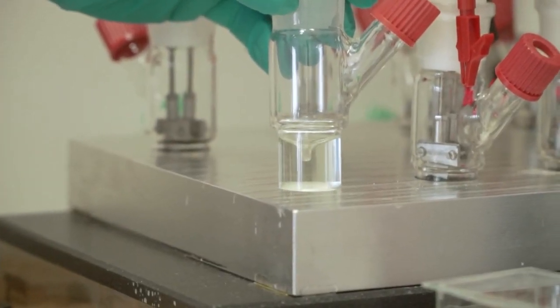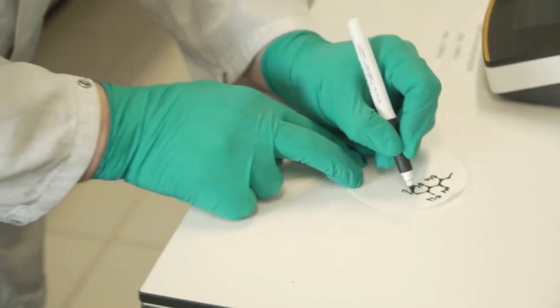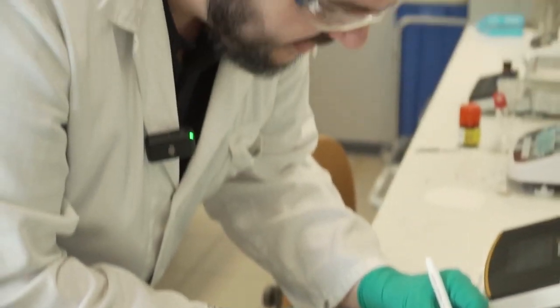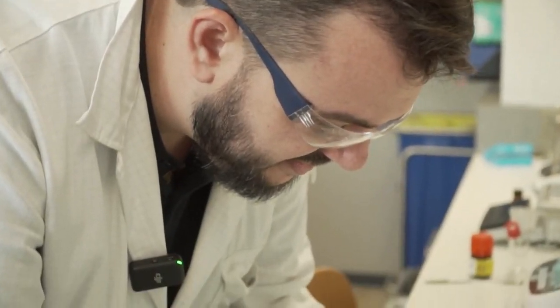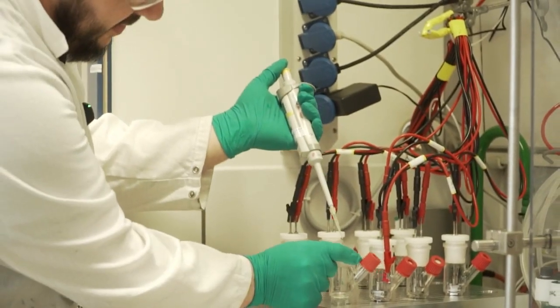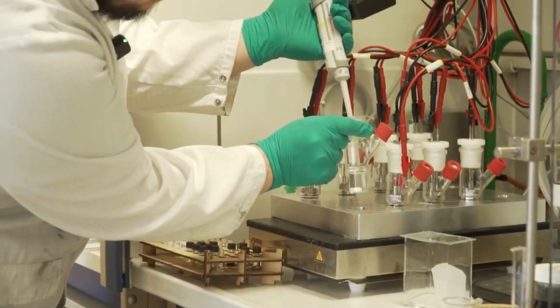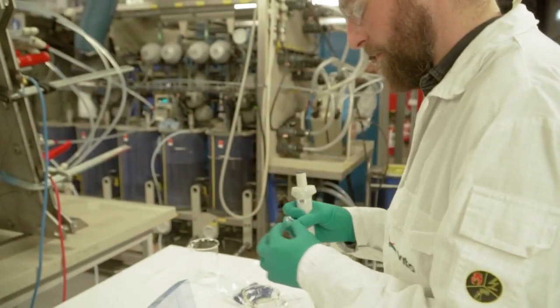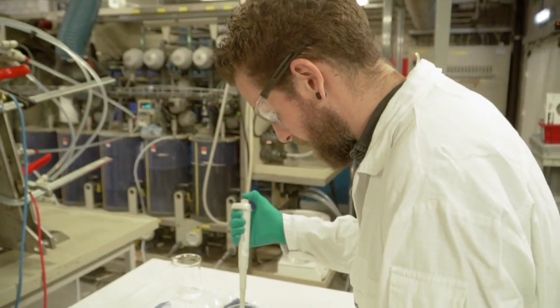This concentrate of gluconic and glucaric acid will then be transferred to a cooling crystallizer, and there we will drop the temperature, limiting the solubility of the glucaric acid and therefore creating precipitates and pure glucaric acid crystals. To further increase the separation efficiency, we add another anti-solvent, as we call it. Actually, it's a solvent that is used to lower the solubility of the glucaric acid in this mixture, which further increases the productivity of this separation.